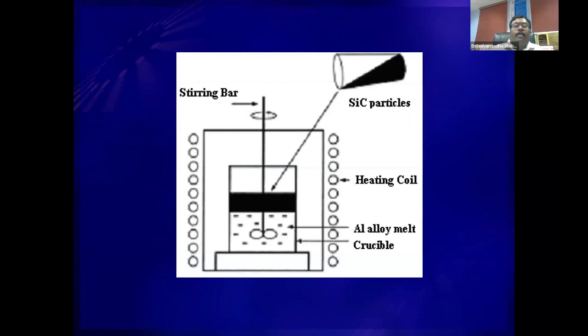The technology is very simple. You heat the metal to make it a liquid and superheat the liquid, and try to add the particles, whatever the reinforcement particle may be, silicon carbide or alumina or any other particle you're going to add, and try to stir it mechanically or probably ultrasonically. So some kind of stirring to create turbulence is necessary so that the particles will be homogeneously mixed and uniformly distributed. Once it is distributed, then by the conventional way of deposition, that means casting solidification, you can do it.